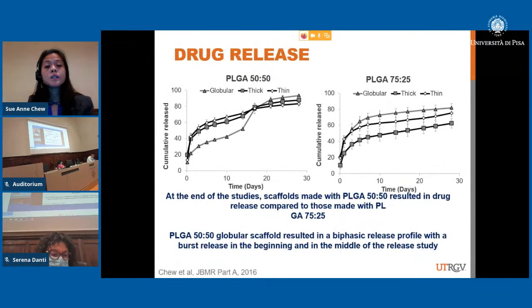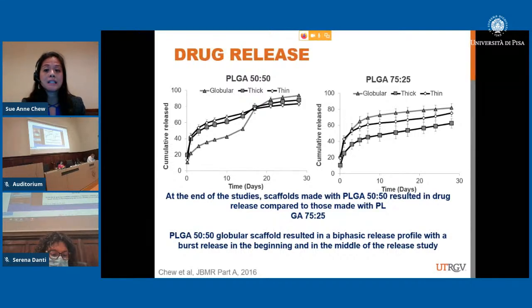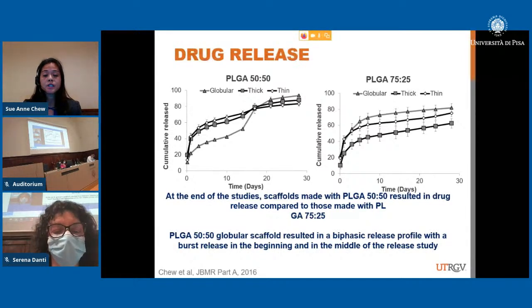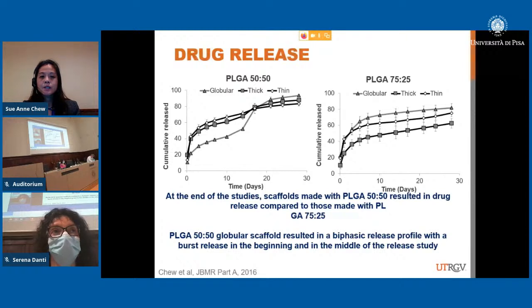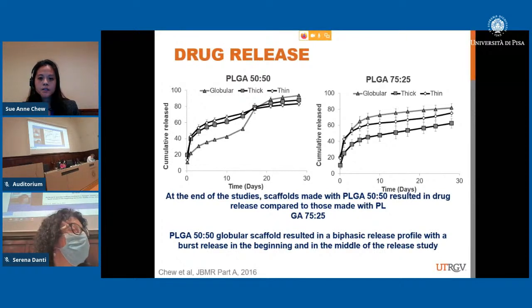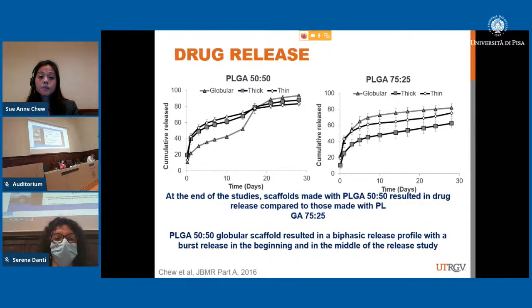So the next thing we looked at was drug release. We wanted to see how changing this SVR would change the release kinetics of the drug. So here, we saw that the globular one again was, interestingly for the 75-25, releasing more drug.